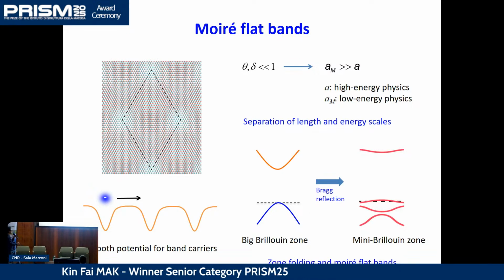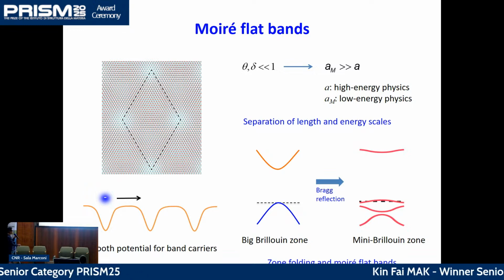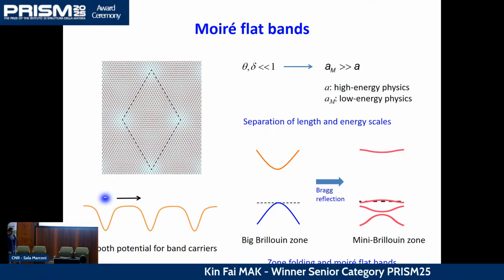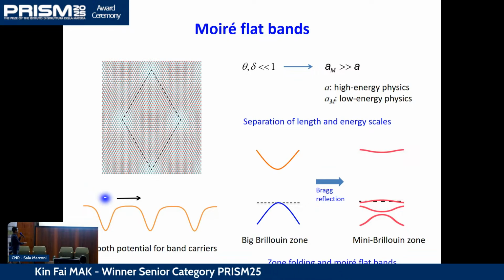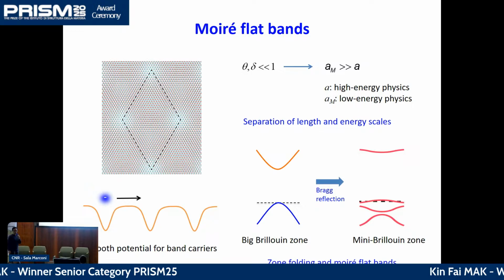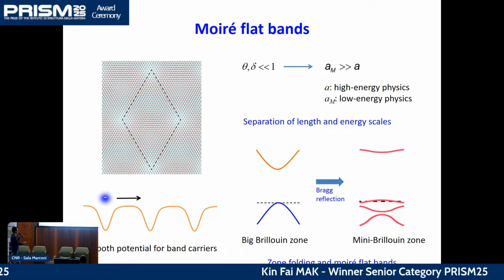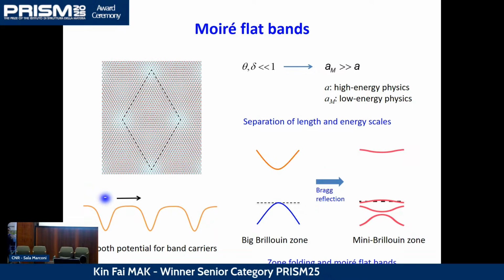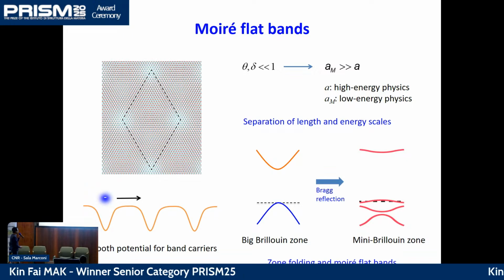You remember that we have a direct band gap in the original material in the big Brillouin zone. With this smooth periodic potential, we can do a zone folding into a smaller Brillouin zone. We call it a mini Brillouin zone. Then the extra Bragg reflection due to the superlattice structure will create this series of flat bands. So you basically go from a band structure like this into a series of flat bands like this in a much smaller Brillouin zone. Okay.